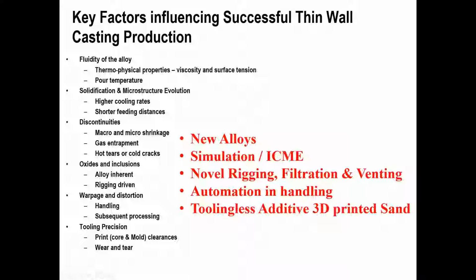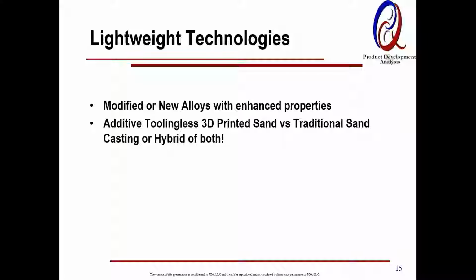This actually is our experience on one of the LIFT project where we did make thin wall castings, but we got only 30–40% at the end of the line. A lot got broken in the tumbling and shakeout operation. So it is a challenge, and you just have to think through and come up with a way of handling thin wall components. And then to completely mitigate and eliminate the issues related to the tooling is the use of toolingless additive 3D printed sand, which really opens up the whole freedom to the design engineers and the production engineers to really go after thin wall repeatedly.